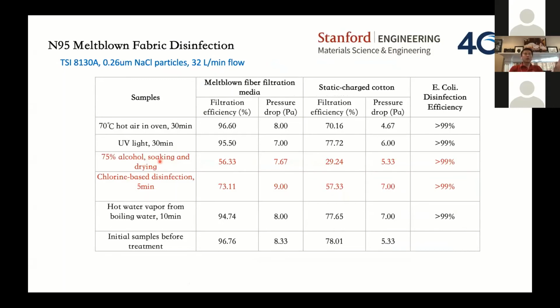If you use alcohol disinfection solution, that doesn't work because it removes the filtration efficiency. More than 95% drops down to 56%, sometimes even lower. And the chlorine-based bleach also made the efficiency drop a lot. So absolutely don't use disinfection solution to wash or disinfect your facial mask, for the N95, because this removes the static charge. For household materials, it's less of a concern, since household material doesn't rely on the static charge, but this is for N95. The steam reduces the efficiency a little bit. I want to point to the hot air treatment, the dry heat, which maintains the efficiency well.